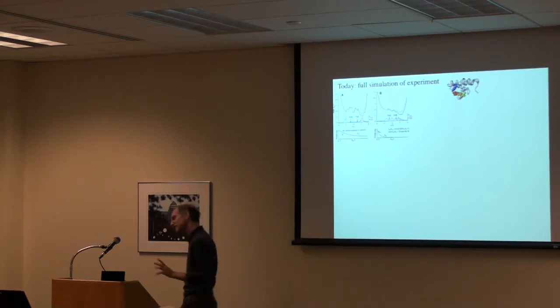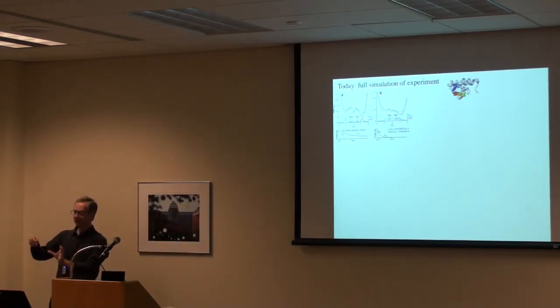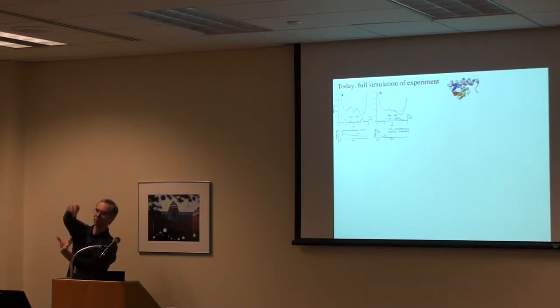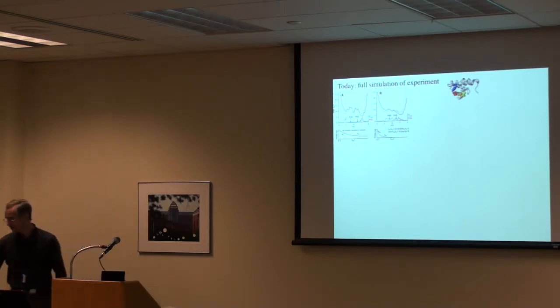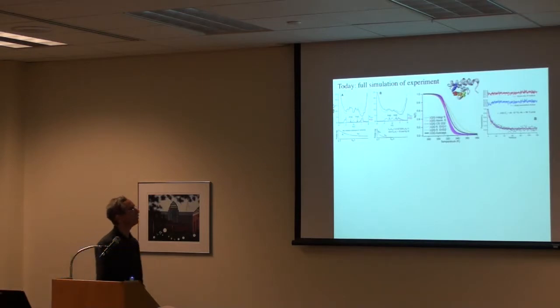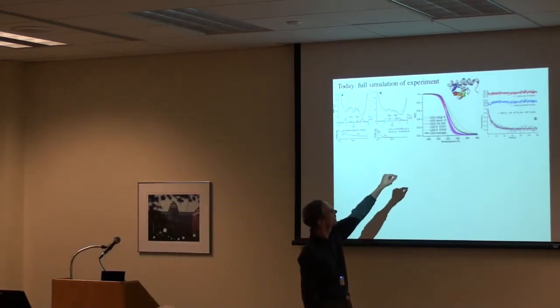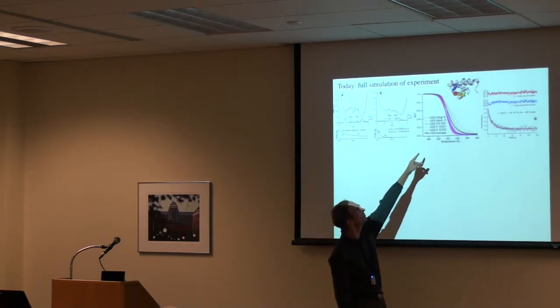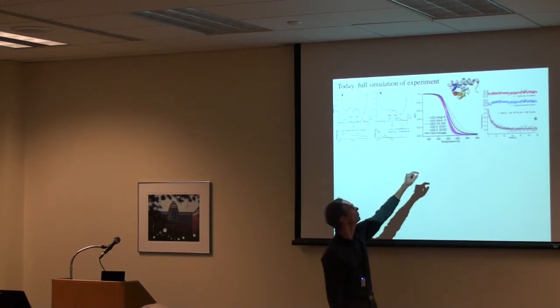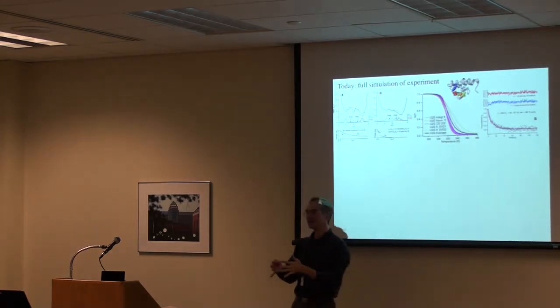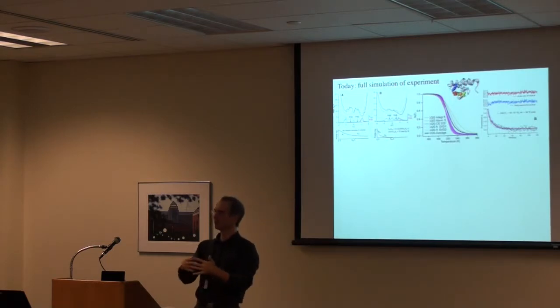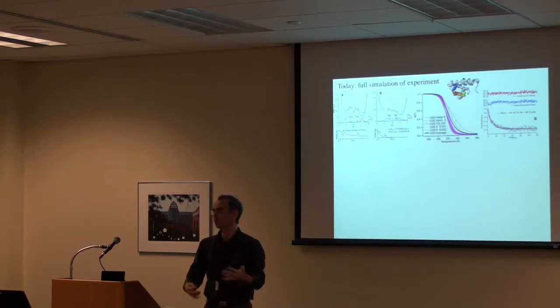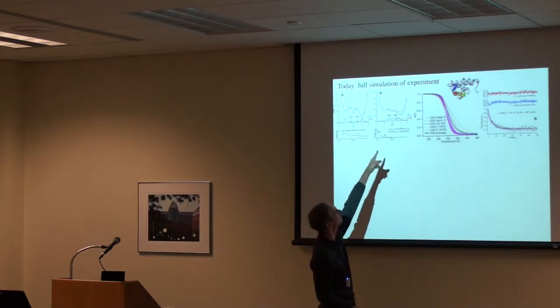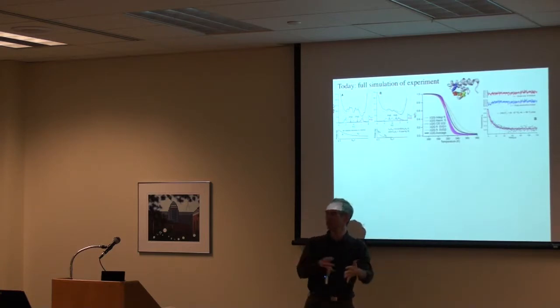And one of the things that's predicted by kinetic theory in that case is that instead of seeing just a kinetic phase that corresponds to the protein moving over from the native well to the unfolded well, you can now also see the diffusive dynamics of the protein as it crosses that intermediate region. Okay, and when you look at that, you get two things happening. First of all, if you look at the thermodynamics of the stability of the protein, you'll find that different measurement techniques, circular dichroism, fluorescence, various other kinds of things, actually give you different answers. So the protein doesn't have one value for what its stability is. It depends on what kind of spectroscopy technique you actually use to look at the protein. And the reason is that different spectroscopy techniques switch their signals at various places along the reaction coordinate, and depending on where you do it, you'll get a different answer.